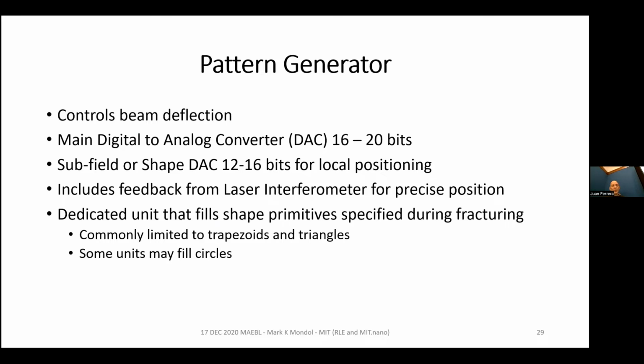So that scanning is controlled by the pattern generator, and that controls the beam deflection, and it's going to have something like 16 to 20 bits. But it doesn't actually scan over the whole field at one time because we're trying to get as many bits as possible to define the grid that we're writing upon. So it subdivides the main field into subfields. And in the HS50, those are 10 micron subfields, and the F125, those are 20 micron subfields. So it's going to go to one subfield and write the information in that subfield, and then it's going to move to another subfield. What I'm trying to get across here is we have this sort of nested DAC situation, so that it's not just 20 bits we have to define shapes, but it's sort of the main DAC and the subfield DAC.